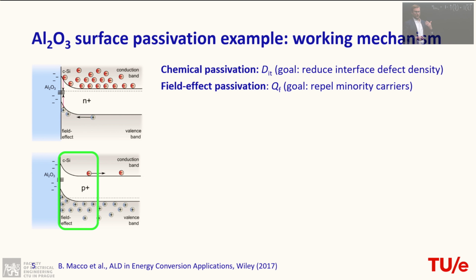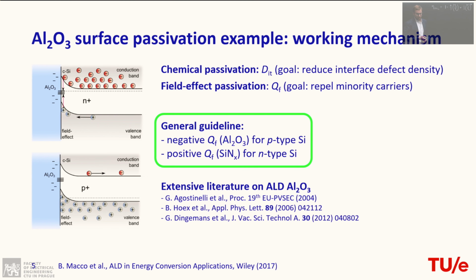What you can also do, and that's happening in the case of aluminum oxide, is that it creates actually quite a large negative fixed charge near the interface, meaning that your electrons are repelled, and the holes can just accumulate there. So that means that the minority carriers are basically repelled, and that means that you don't have both carrier types present at your surface, meaning that the chance of recombination is just reduced. So this QF parameter is important to increase, so you repel your minority carriers. So the general guideline is that we want for p-type silicon to have a negative QF, for instance aluminum oxide, and for n-type surfaces people use silicon nitride to get this positive QF realized on the silicon.